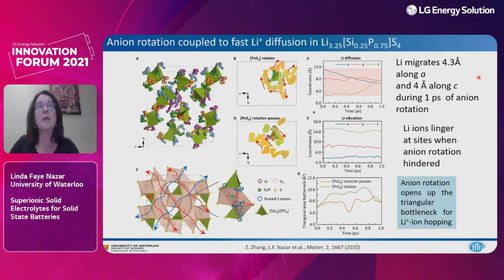And we furthermore carried out these ab initio molecular dynamics simulations to understand exactly how this works. And we can see again, this is the green tetrahedra here, the PS4 or the SiS4 tetrahedra. This is a 1 picosecond snapshot. You can see the sulfide ions moving through their trajectories in this framework. Just to make it a little easier, in this diagram it's described in 2 dimensions. And so you can see the mobility of these sulfide ions whipping around on their central phosphorus or silicon tetrahedra.